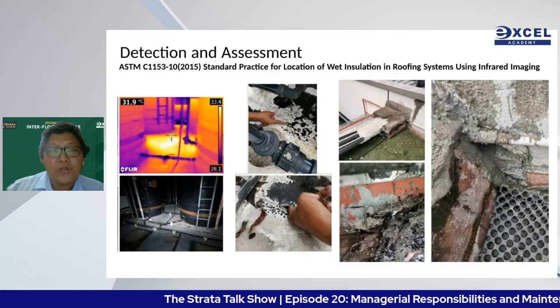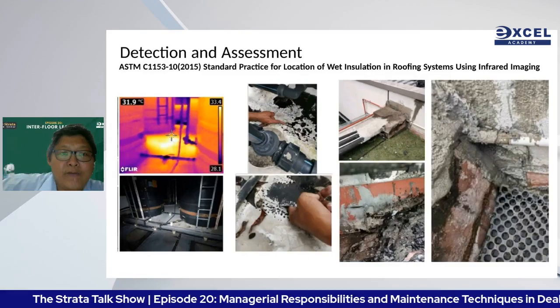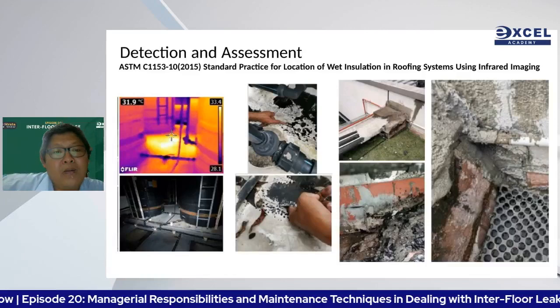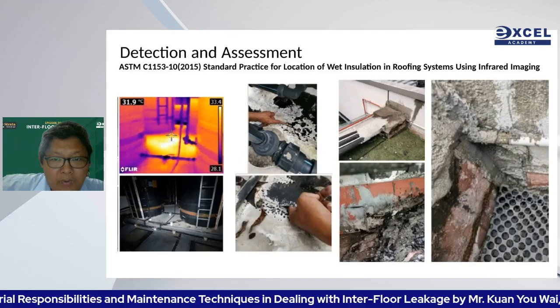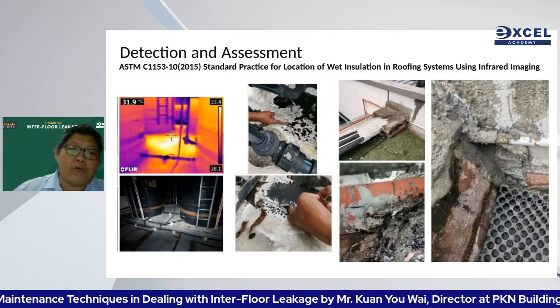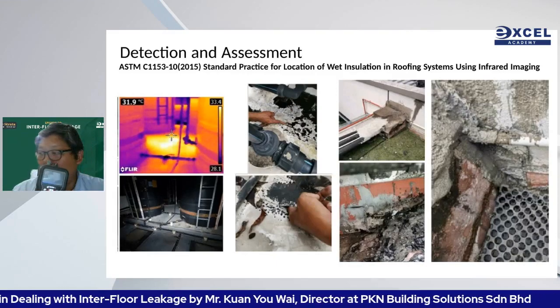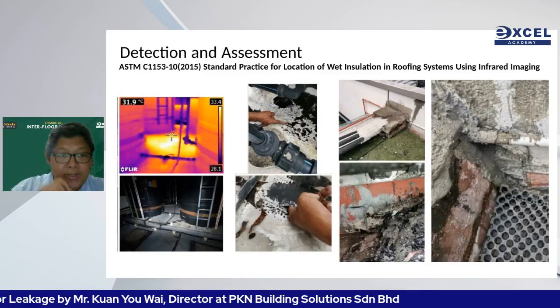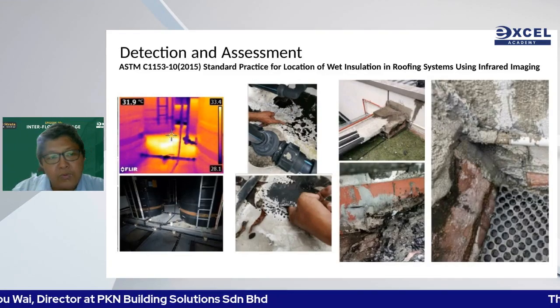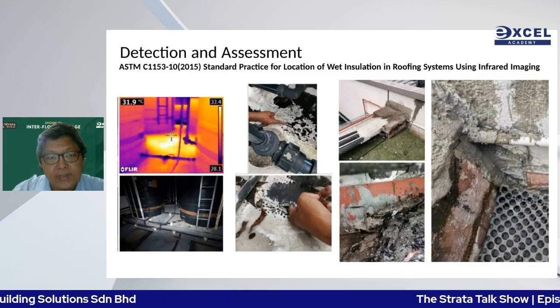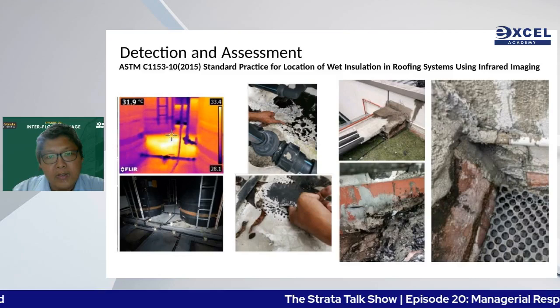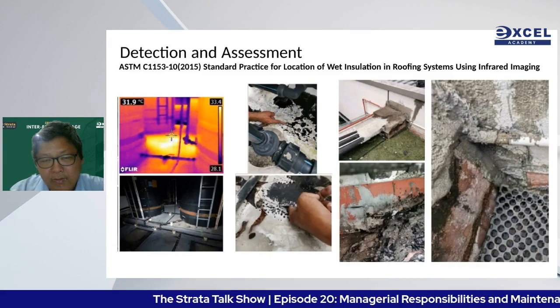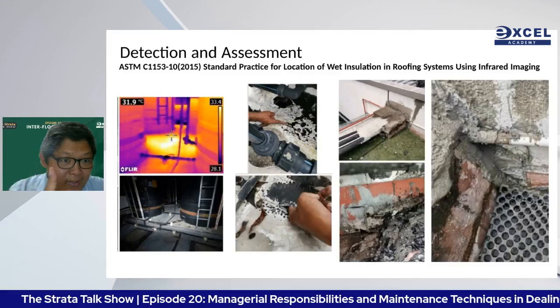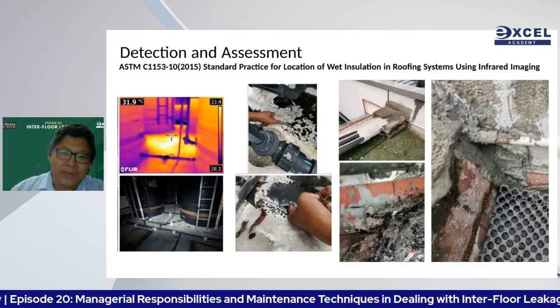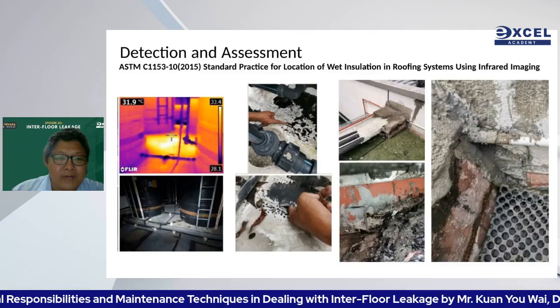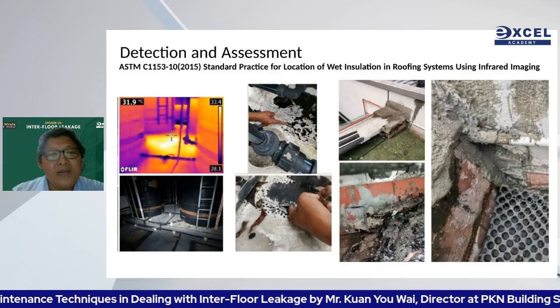So at night, 8 p.m., based on ASTM C1153, we do infrared imaging to detect the water pocket and to confirm it with this type of capacitance type of moisture meter that can penetrate up to 20 mm from the surface to confirm the presence of the water pocket. So this is a scientific way of identifying leakage. And in this case, the leakage is due to the cavity. We found poor workmanship and poor termination at the piping penetration. So, okay, next slide, please.